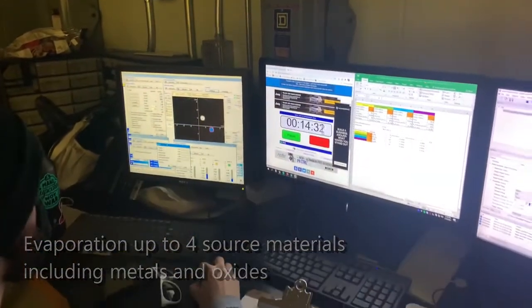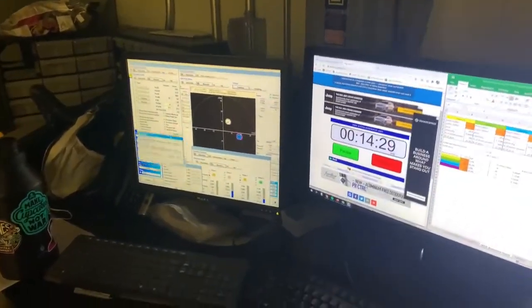And so we can in situ decide where our electron beam hits it with how much power, and as a result, it's a bit bright. We actually see our source material getting evaporated down there onto the substrate up there. Let's actually see if this works. Yes. We see our substrate getting heated up to about 1200 degrees C up there. And then the blue, what you see down there, is actually evaporation of the material.